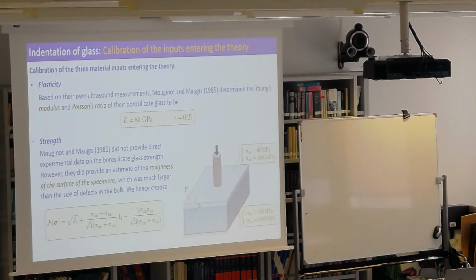So this is how we're going to model it. We realized that if the defects on the surface are very large compared to the bulk, the strength on the surface must be smaller than in the bulk because the defects are larger, right? That's our interpretation of strength, the behavior of defects macroscopically. So we use Drucker-Prager. Now, is Drucker-Prager a good model for glass? I don't know. You have to do experiments, right? Again, this is a macroscopic theory.